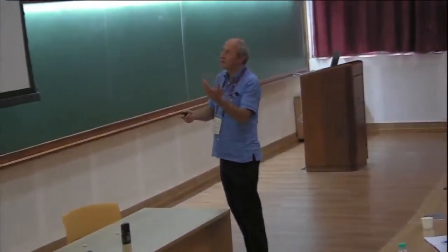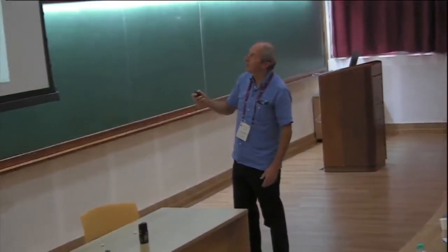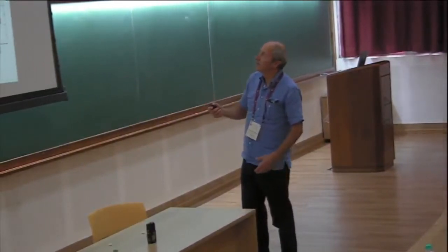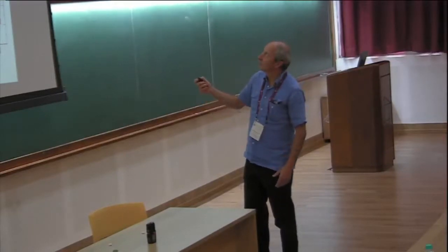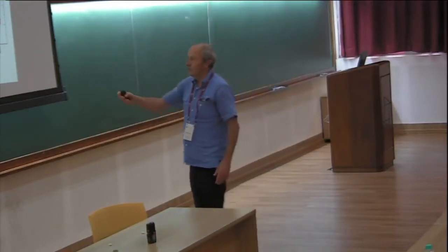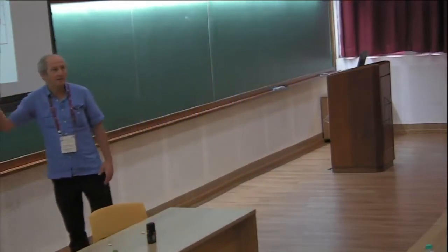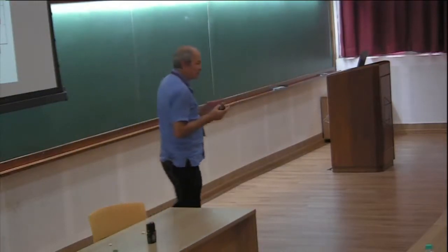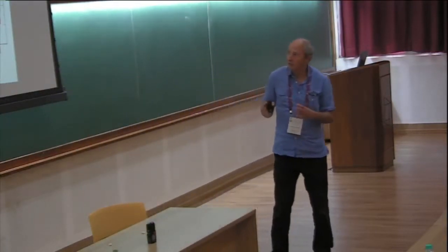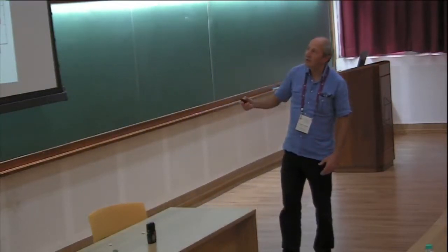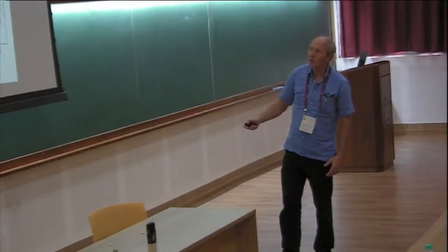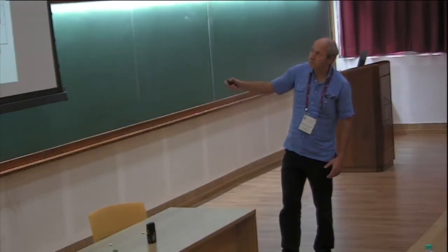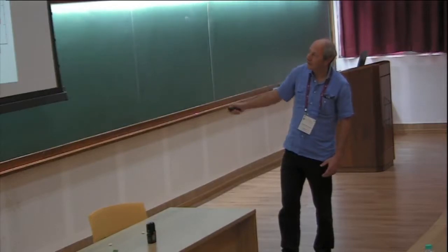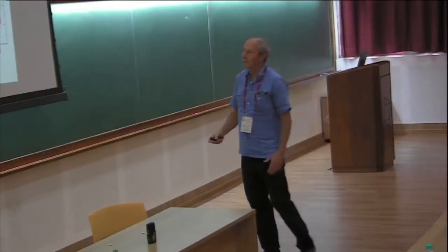We have collected several models that have been studied of particles which can form 4 patches or 4 bonds. And I put together also silica, BKS silica, and 2 models for water, ST2 and SPC/E. If you scale the density according to the nearest neighbor distance, so that everything is controlled by the same unit, then they are all very similar. Those are soft matter type models, and those are atomic models, and they are really very similar.